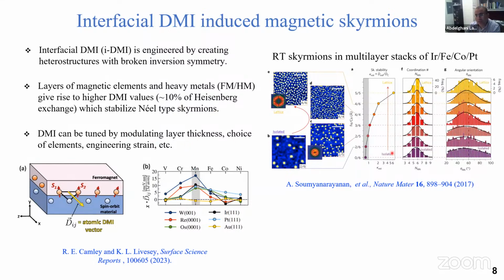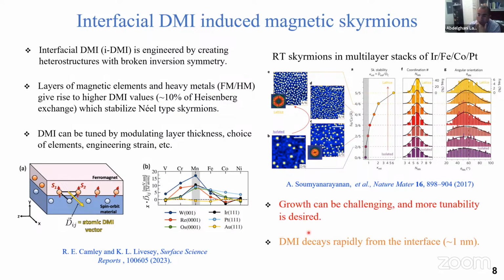The advantage of these systems is that you can observe room temperature skyrmions, isolated for example, by increasing the magnetic field or by changing the heavy metal, you can go from isolated skyrmions to a skyrmion lattice. In this example, you can get this skyrmion lattice, which is very interesting in terms of high density memory applications. For these systems, I put this in red, the growth can be challenging.